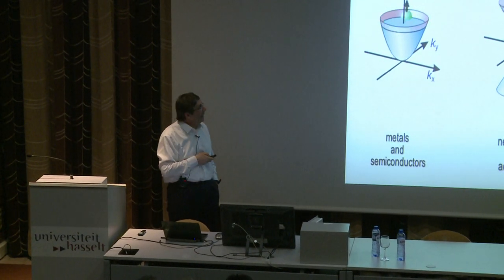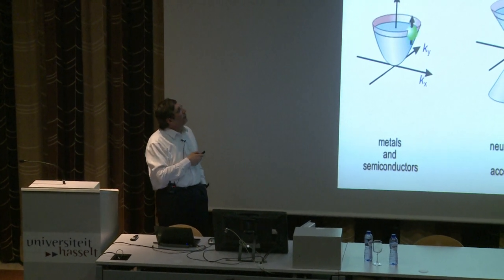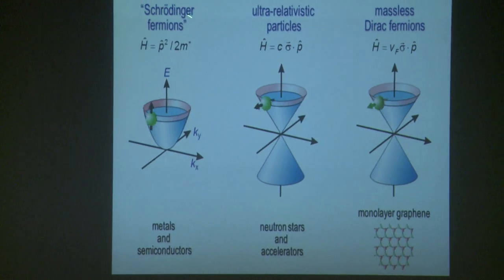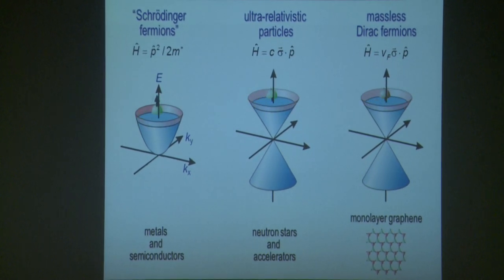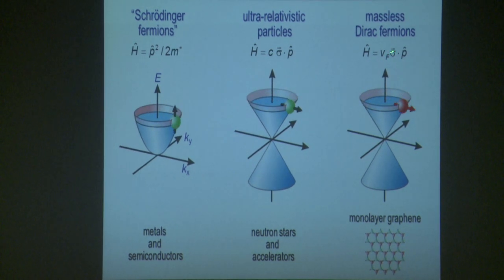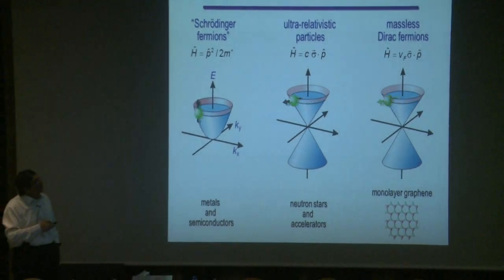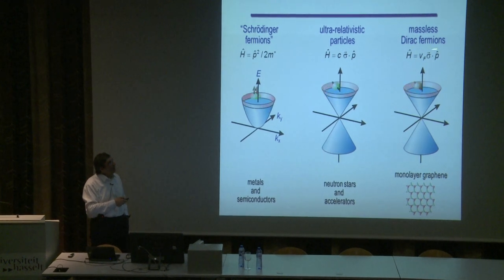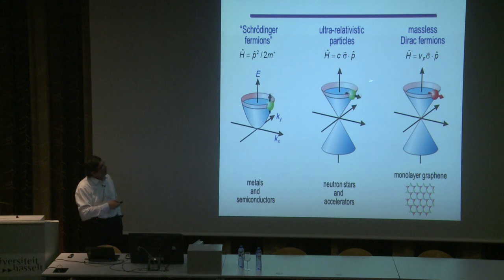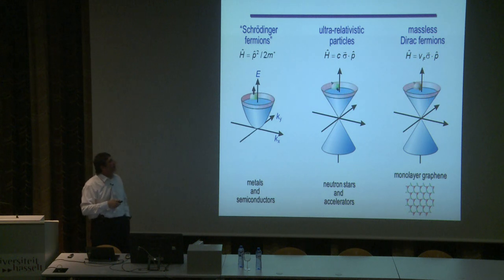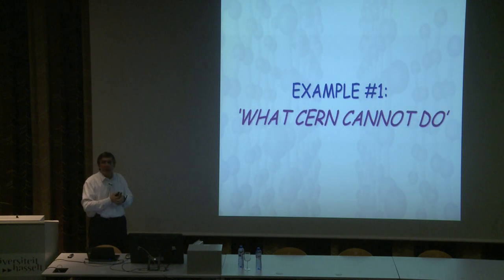So where graphene comes into play, in graphene, it turned out that this mass goes to zero. Essentially, it goes from normal speed to particles which are moving very fast, not with the speed of light, but with a very high speed, 300 times slower than the speed of light. But the interaction of electrons with the carbon lattice has to be described by this equation, which mimics, it's not the same equation, but it mimics what particle physicists and astrophysicists can observe. So immediately, due to this strange play of physics, and because it's a chicken wire hexagonal lattice of one carbon atoms, you'll get something which is like CERN, but on your desktop.